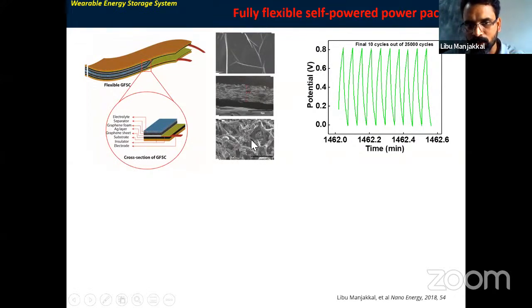It's a 3D structure, so the major advantage is that it has more electrolyte interaction. You can see the cross section here: there is a substrate, and then a graphene sheet acts as a current collector instead of platinum or other metal-based current collectors. I used graphene because it gives more flexibility. And then graphene foam, with phosphoric acid as the electrolyte. You can see that it shows more than 25,000 charging-discharging cycles. That means it can operate for many days. This is the advantage of a supercapacitor.